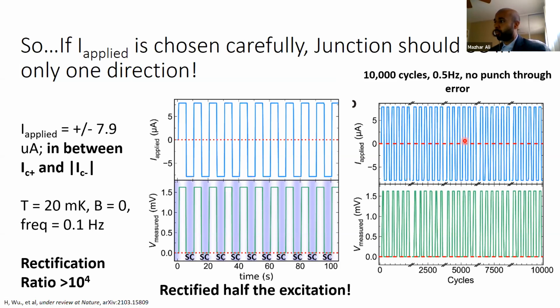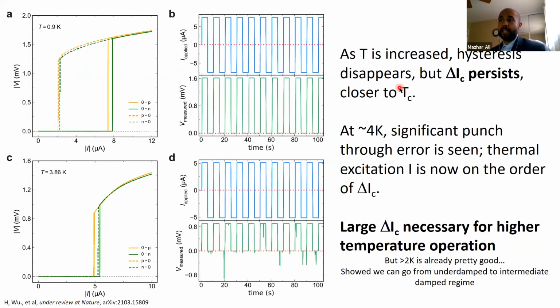It really just works. It follows the applied wave. Again, it's not that many, but it proves the point. 10,000 cycles, not a single punch through error. So it's very stable at that temperature. Now, of course, as we increase temperature, get closer to TC, this changes. So at 0.9 Kelvin, so nearly a Kelvin, this is still working exactly as expected, as it's described before.